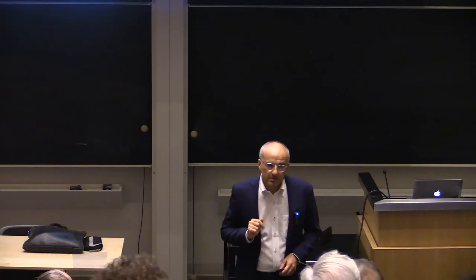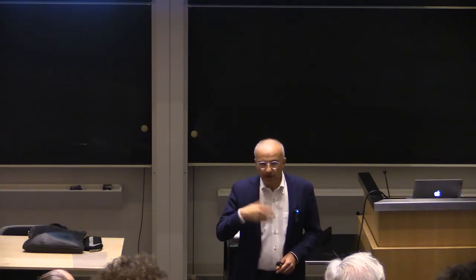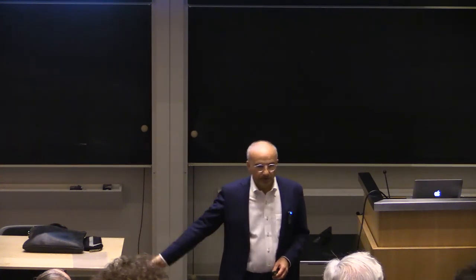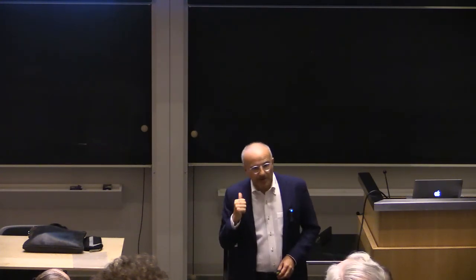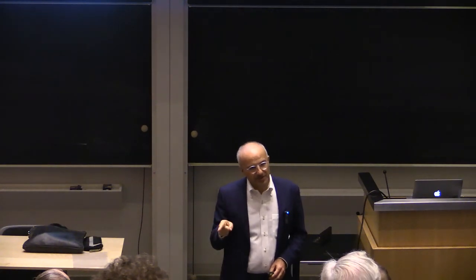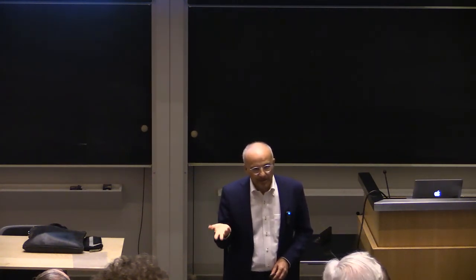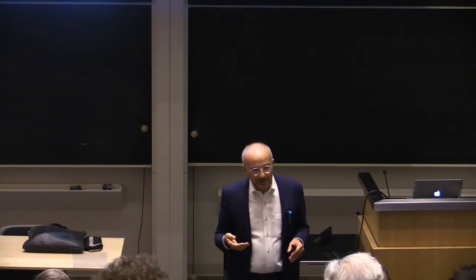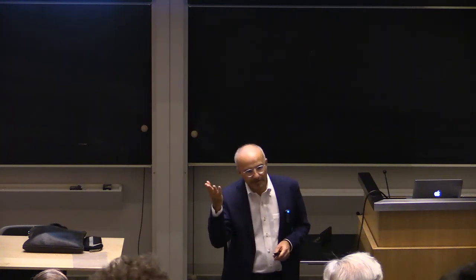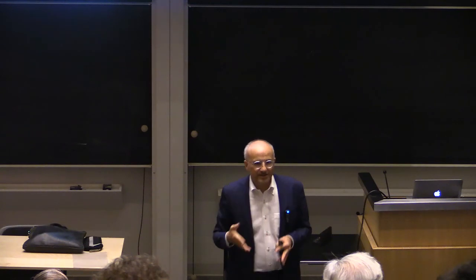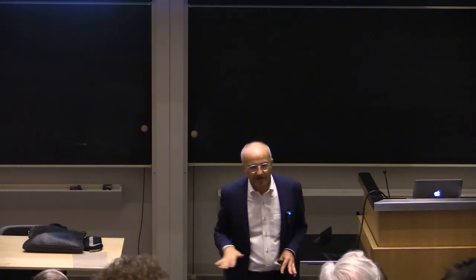But we can handle it when the system has sufficiently high crystalline symmetries, for a reason that I don't have time to discuss. When we go from a D shell to an F shell, that becomes difficult. On top of that, most of the calculational schemes that we have by now for D shells or F shells are Monte Carlo based, which means that they all live in imaginary time. We do a Wick rotation. Spectroscopists don't like imaginary time. They make real frequency measurements, and this is the infamous problem of analytic continuation. Ideally, we would like real frequency and perhaps real-time solvers to do non-equilibrium that are able to handle a D or an F shell. Nobody is there yet that I know of.